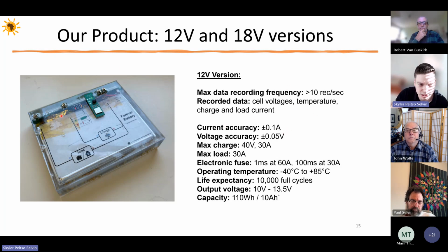The current accuracy of the measurements, from the sense resistor, is about 100 milliamps. The voltage accuracy on each one of the cells is about 50 millivolts. You can charge it probably greater than 30 amps. We've been experimenting with that, but at least at 30 amps continuous charge, and discharge at 30 amps. And you can put as much as 40 volts on the terminals without it damaging the battery. And this is generally larger than any solar panel that you'll find in Africa.